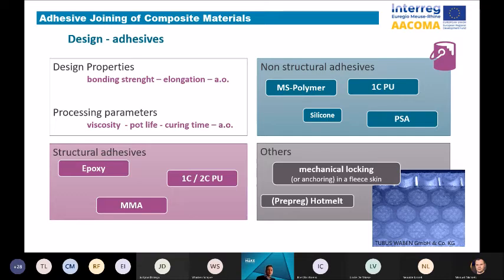As I told you, composites with a thermoplastic matrix, especially the polyprop, have a very low surface energy and are challenging to bond. But making use of a fleece can be a solution for this. This fleece is part of the composite layer, of the top layer of the composite, and the adhesive will be mechanically anchored into the fleece as the bonding force.